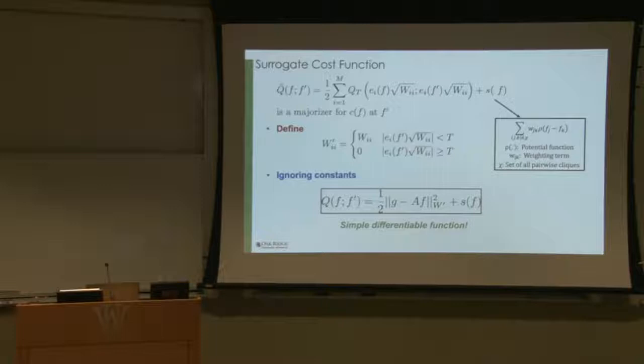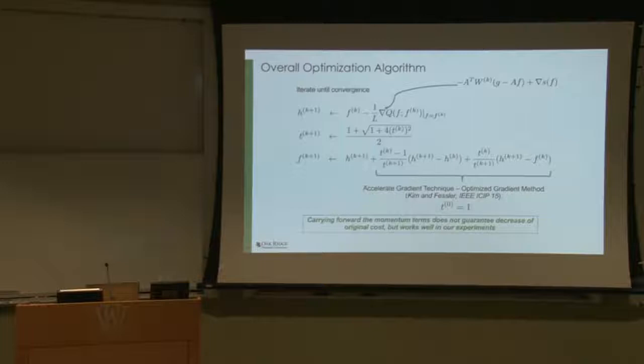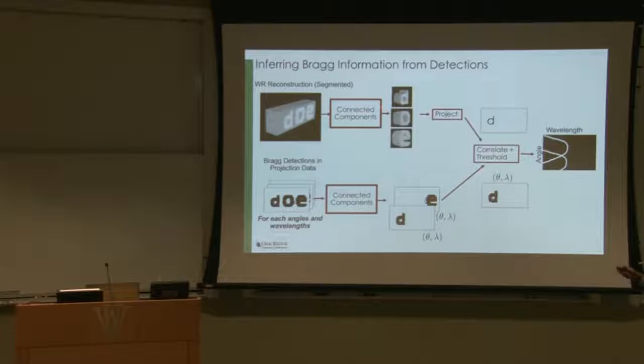That's the algorithm in words. But essentially, that's what it does. And you can keep repeating this, construct a surrogate, lower it. And at the end of it, you get a reconstruction and a map of measurements that were rejected out. So once you build that, you can then use any technique to optimize the inner problem. I've used a standard method from the literature, based on taking a gradient and just taking a step with some acceleration. So once you get the reconstruction, then you can segment it.